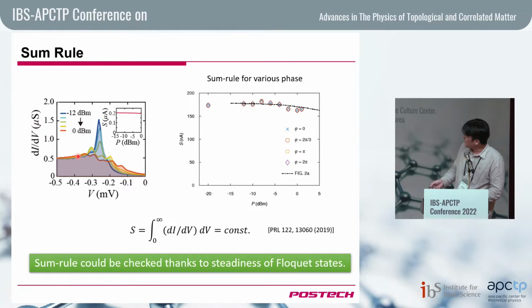So if the Floquet state appears at even higher energy, although we cannot resolve it here, then that will contribute to the leaking of density of state away from our integration range. So I think that's just an artifact. If we measured a larger range, that decrease can be cured, I think. So that's one thing we were able to do because we shine the continuous microwave, we can measure the details of the spectrum, so we were able to confirm this sum rule.